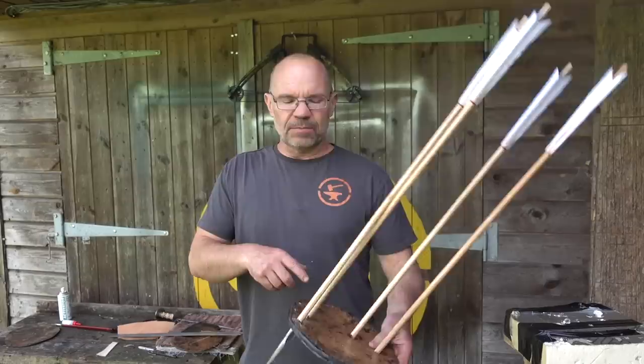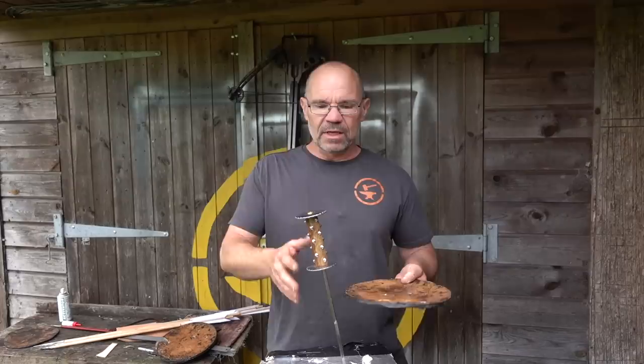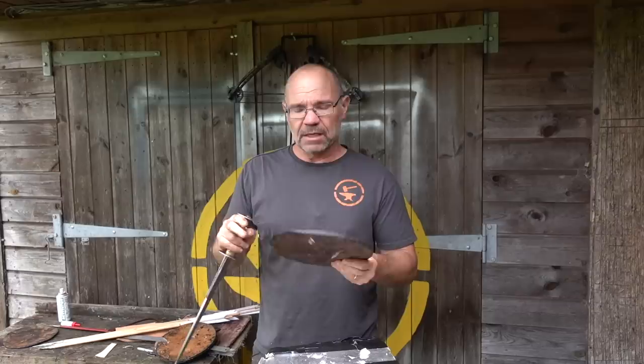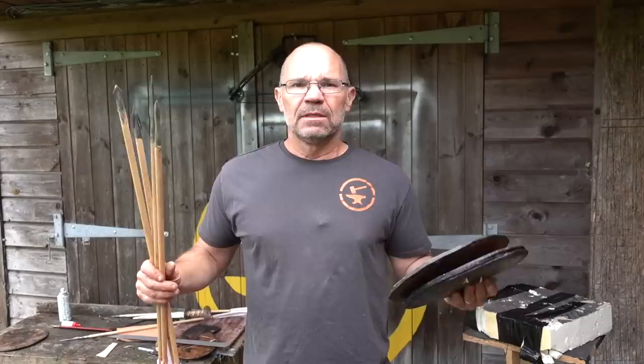There's one more thing we're going to do — we're going to go back to my stab test with the rondel. I've removed the arrows from the two-ply piece and we're going to go for the stab test again with the Todd Cutler rondel — remembering these are all available and really do help support the channel. So that's penetrated about a centimetre — good defence. So anyone who says hardened leather is not good, they're wrong. We'll try that again with a three-ply, just to see what we do. And that one maybe about six millimetres through, so that without a doubt is not a killing blow — well nor is the other one, neither of them are. They're going to hurt a bit.